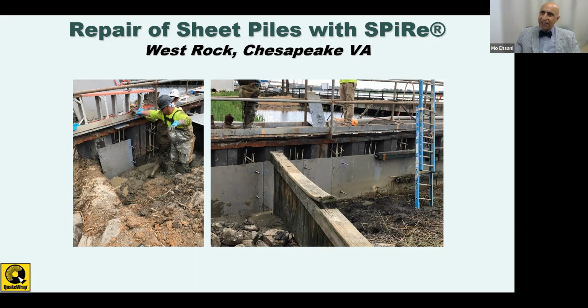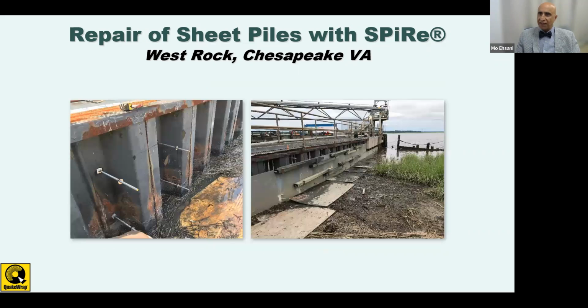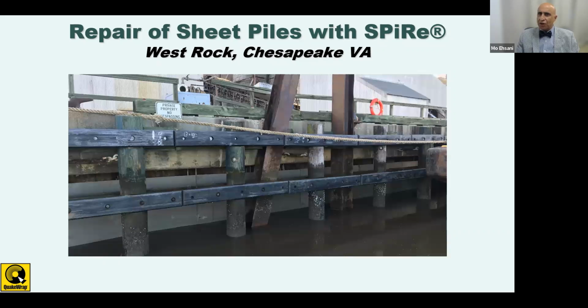And you see behind the wall, there are also the glass FRP rebars that are put inside of those cavities for additional strengthening. And we can use these whalers on the back of them, just as a temporary support during the placement of the grout. So as you notice, the FRP wall has been created in front of that, behind that overhang.